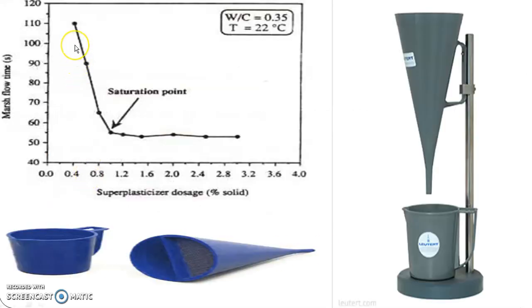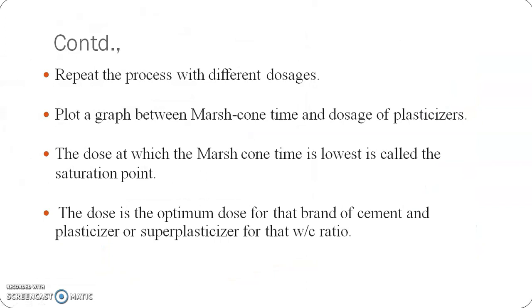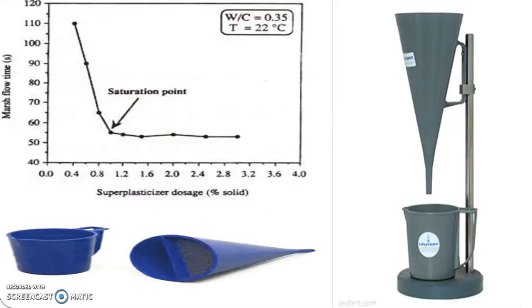This is shown here. Different Marsh cone timings are found for different dosages of plasticizer. Here the plasticizer dosage is 0.4, 0.8, 1.2, and the flow time varies from 110 seconds, 90 seconds, 70 seconds, like that you are measuring the time. The lowest point will give the saturation point. That dose you have to take as the optimum dose for that particular brand of cement. Likewise, we can find out for the various brands of cement the optimum dosage of super plasticizer for the particular water cement ratio.